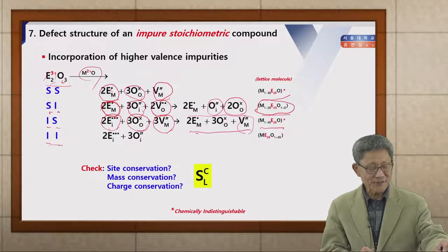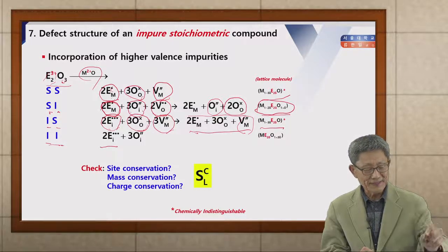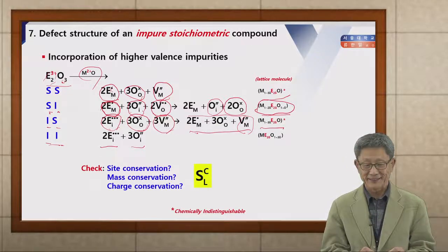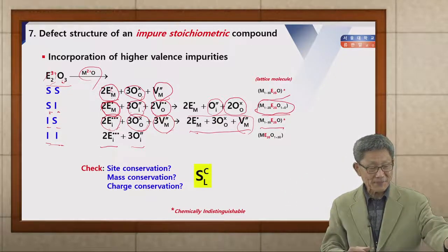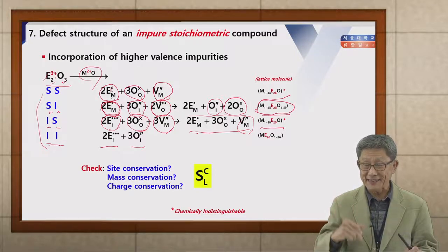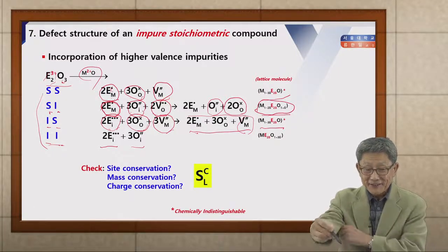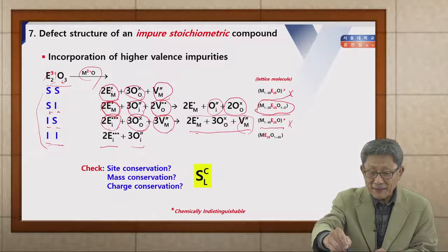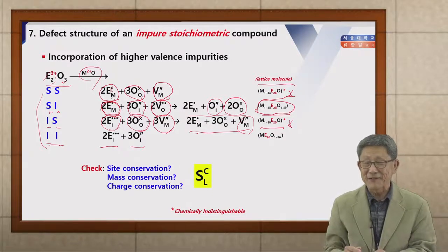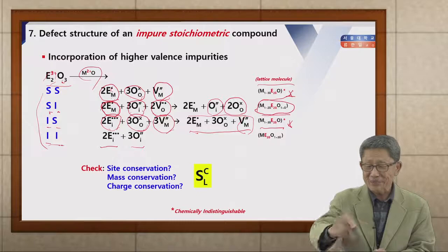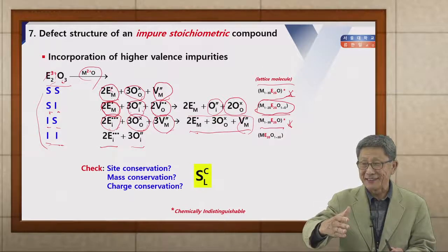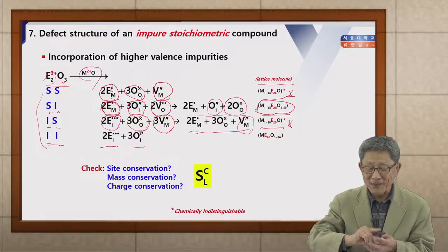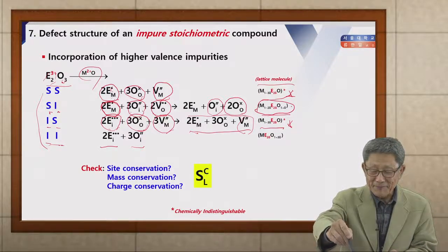And the last case is trivial again. You see, the cation goes to an interstitial site, and oxygen also goes to an interstitial site. So we have only 4 possibilities for the case of a binary system. Okay? But here you can easily see that the first possibility and the third possibility have the same lattice molecular formula. So these 2 possibilities cannot be distinguished chemically. Therefore, the existing possibilities are only 3, okay? Namely, either one out of this one and that, and the rest 2.